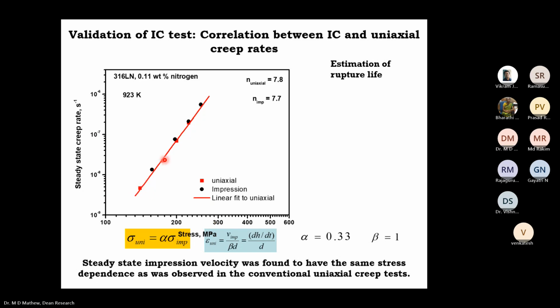The red square data points represent the uniaxial creep test from the standard test, and the circles represent the impression creep test, and you find that there's a very good correlation and the slope is the same. So now you find that you are able to convert the impression creep test data into the data that you would have otherwise obtained from a standard creep test.